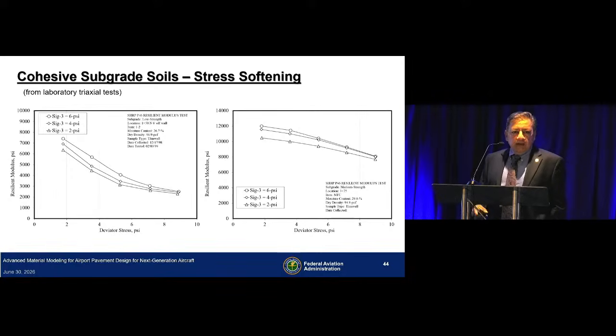Let's move on to the subgrade soils. What you see on the left-hand side are the results from low-strength subgrade, which is a silty clay. And what you see on the x-axis is the deviator stress and resilient modulus on the y-axis. So again, these are results from a triaxial test. And you can clearly see as your stress increases, the modulus decreases, and that's what we call stress softening behavior.